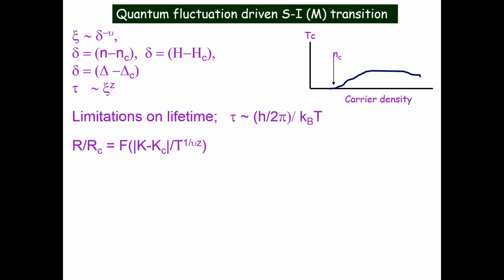So now I can write the behavior of the resistivity in the critical regime by using the scaling argument. Here you write the parameter that you are changing, k minus k critical, which could be the field, could be disorder, or could be carrier concentration. And then in the denominator you get temperature and these two exponents.